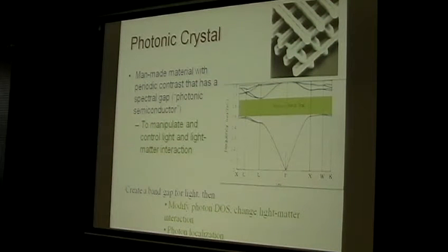So a lot of things that you can play around with just in the long wavelength limit, and then of course when you go to the regime in which the wavelength matches the scale, you have very strong backscattering. In some cases, this backscattering can be so strong that you open up a band gap. A band gap means a place in which you have no mode. If you look at the density of states, there is nothing particularly interesting up to there, then you will see a very high density of states, and then suddenly it will go to 0. And of course, if you can control density of states, there are a lot of things you can do, because by the end of the day, how matter couples depends on the density of states in the medium that you're talking about. And therefore you can control a lot of optical processes by controlling density of states.